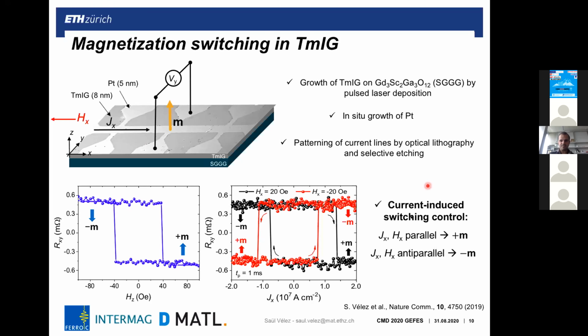So this tells us that we can control the final state of the magnetic system by applying current pulses and a magnetic field in plane. When they are parallel, we stabilize up magnetization, and when they are anti-parallel, we stabilize down magnetization. This is simply because of the symmetry of the damping-like torque in this heterostructure.